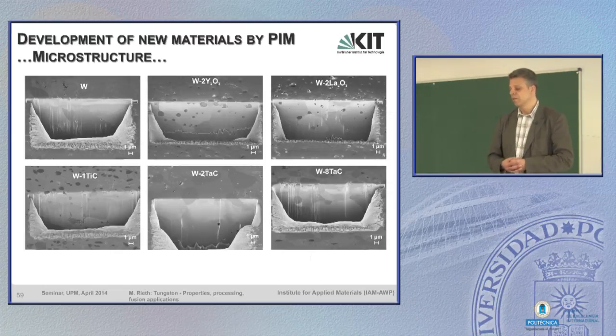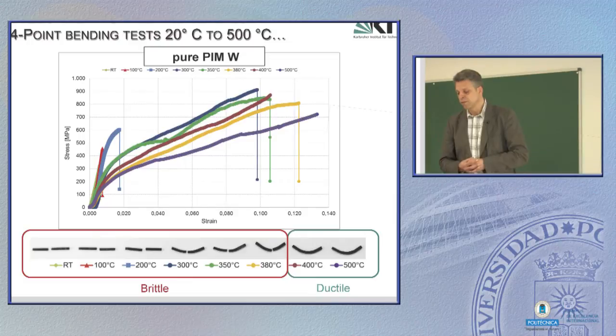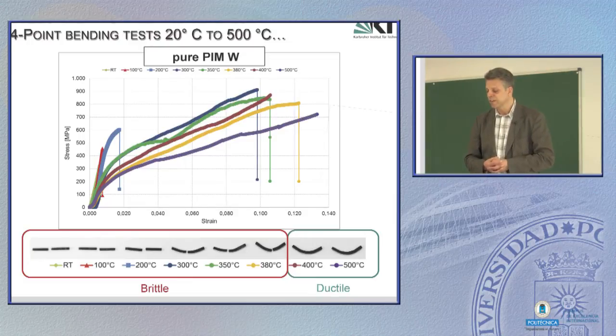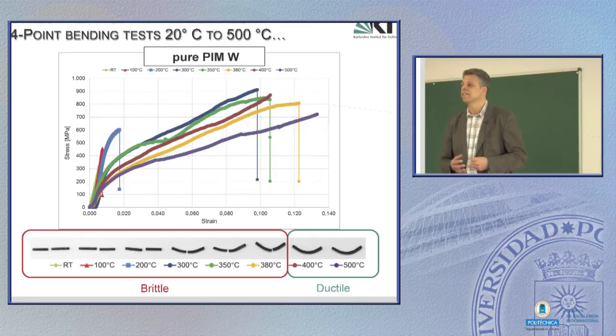And to have a rather quick overview on the behavior, we use 4-point bending tests with a low strain rate, so temperatures up to 500 C are already sufficient to see what happens. And in pure tungsten, you see it down there. At a very low temperature, we have rather brittle fracture without any plastic deformation. At 300 C, the specimen will start to be bent, and well, at 400 C, there is a sharp transition. 380, 400 C, the specimen doesn't break anymore.